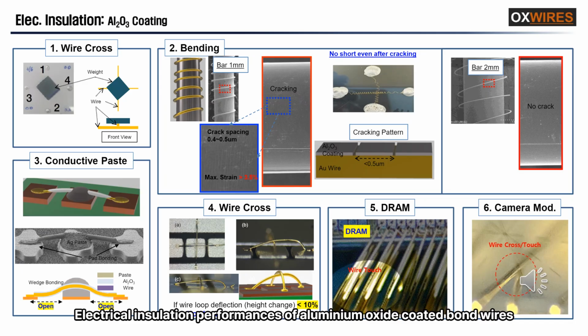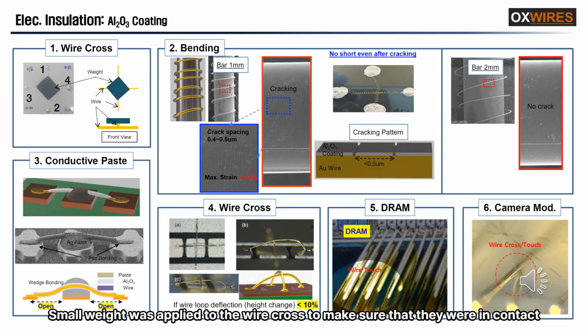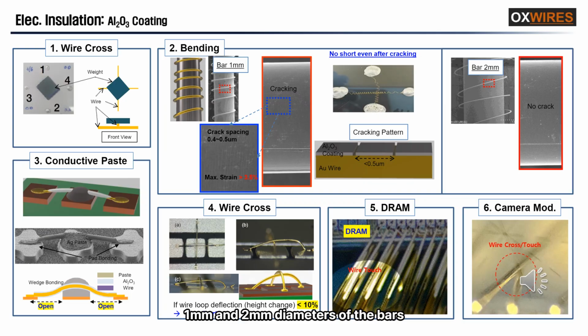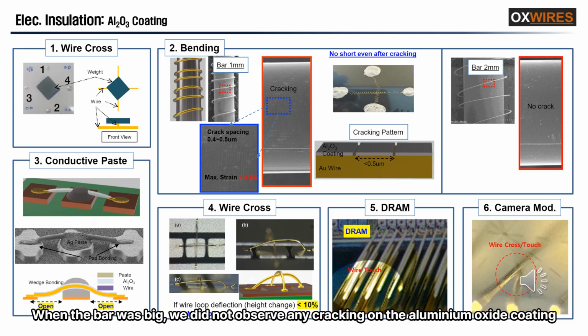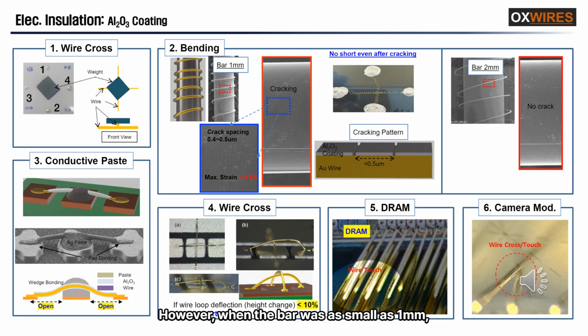Electrical insulation performances of aluminium oxide coated bond wires. First, simple wire cross. Small weight was applied to the wire cross to make sure that they were in contact. No short. Second, aluminium oxide coated wires were wound around small round bars, 1 mm and 2 mm in diameter. When the bar was big, we did not observe any cracking on the aluminium oxide coating. However, when the bar was as small as 1 mm, cracking occurred on the aluminium oxide coating on the wires. Crack spacing was about 0.5. The maximum strain of the aluminium oxide was found to be about 3.5%.